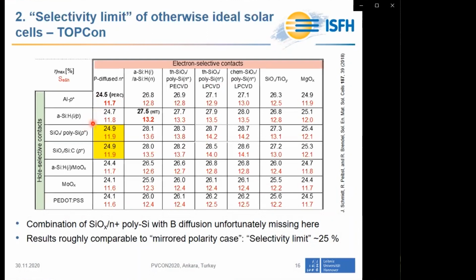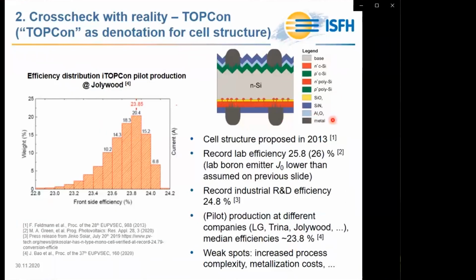The mirrored polarity case means the combination of a phosphorus diffused N-type frontside emitter with a P-type hole collecting polysilicon oxide junction. And for this combination, the combined selectivity is around 12 and the corresponding selectivity limit close to 25%. For such a TOPCon cell, as illustrated here, industrial record efficiencies up to 24.8% have been announced. This is pretty much consistent with our selectivity screening.